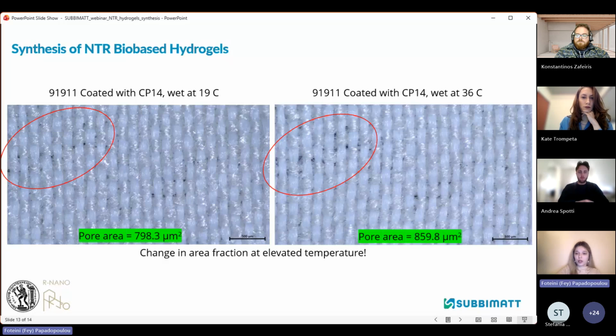So we did a hydrogel that has 50% bio-based content using the HPMC, the polysaccharide we are using. It is temperature responsive, and we use it to create smart textiles. We tuned its mechanical properties to process it more easily with different techniques, either injection or just butter coated, and we have this result.